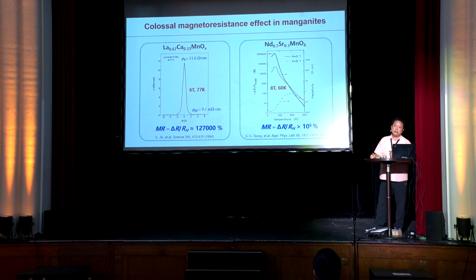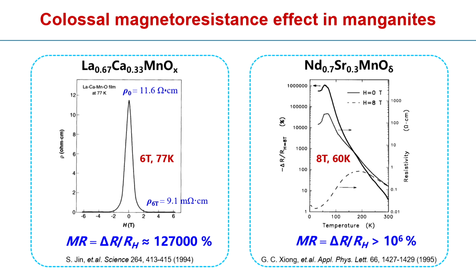So you can see that for all these milestone works in the development of spintronics, the key is the order of magnitude increase of the MR. Whenever you get an order of magnitude increase of magnetic resistance, you can generate some kind of major impact in the field. That's why there was a huge excitement when the CMR effect was reported in the manganites, which are old materials that people knew in the 1950s. But then in the 1990s, two papers reported very high magnetic resistance, even in the original report already like 4 orders of magnitude larger than the GMR or the TMR effect. So it's a really large magnetic resistance.